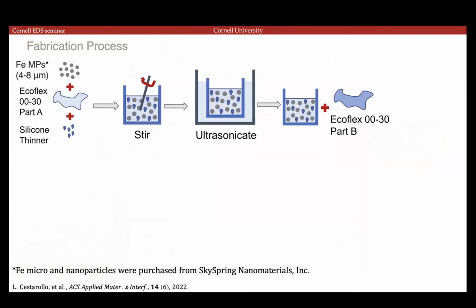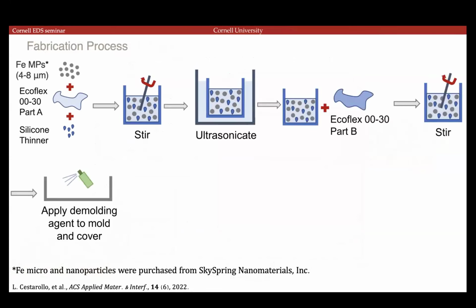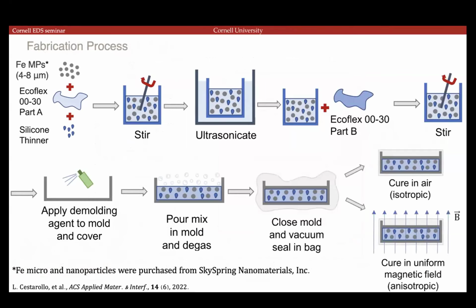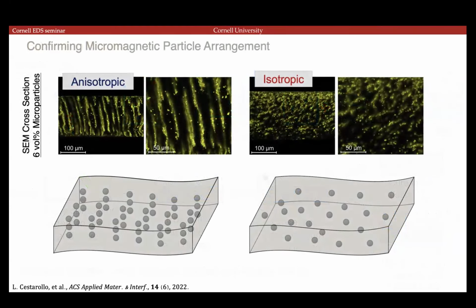When people take iron magnetic microparticles, which are 4 to 8 microns in diameter, they mix them into elastomer, making sure it's very well mixed. Then we put it in some sort of mold to take the form and make sure to degas it. In the very last step, we can either cure it in a magnetic field so that the film becomes what we call anisotropic, so the magnetic particles chain up, or the film becomes isotropic. If there's no magnetic field, the magnetic particles are randomly distributed in the film. The actuation response to a magnetic field is very different for each of the two films. This is a quick SEM image showing that we were able to achieve those isotropic and anisotropic arrangements of the particles in the elastomer films.